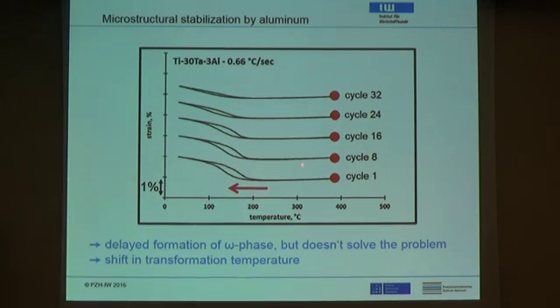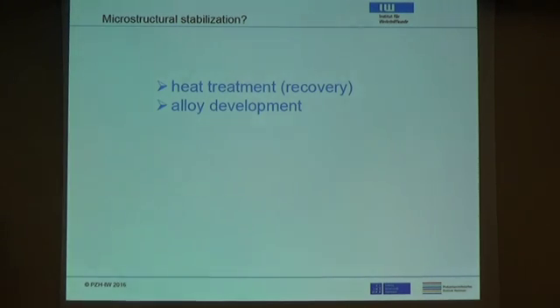And there's another problem. Remember, without the aluminum, we had a transformation between 200 and 300 degrees C. And now this is shifted downward, so around 100 to 200. So aluminum additions do not really solve the problem. So what can we do? We came up with 2 ideas. One is heat treatment. We call this a recovery heat treatment. And the other one is further change in alloy composition to basically stabilize the microstructure.